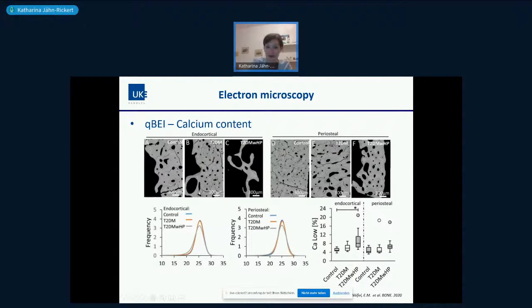So then she looked for the calcium content, and what one can see here is that between the control and the type 2 diabetic specimens, the calcium content is really similar in its frequency distribution at the endocortex, but also on the outside, at the periosteal side. There was a third group that maybe now out of interest I should mention. So she defined within the type 2 diabetic patients a subgroup where the patients had a very high porosity. So you see that also here. And those had a lower average mineralization profile. You can also appreciate that here there are certain parameters that one can look at. The calcium low was higher, meaning that there are more lower mineralized areas in these specimens.